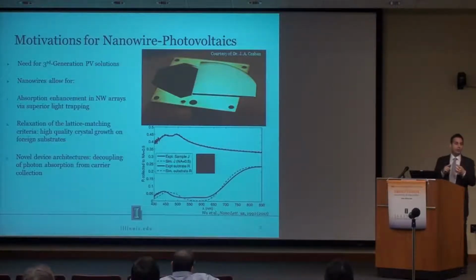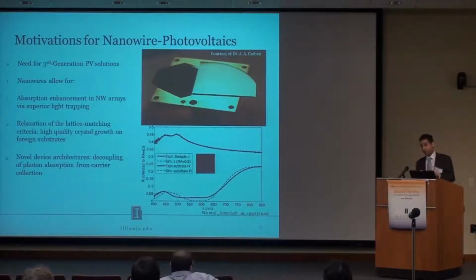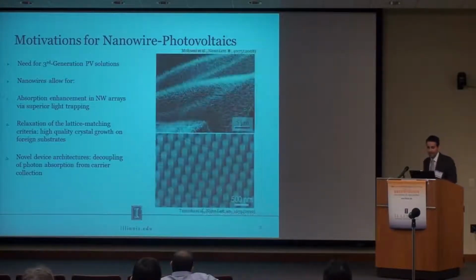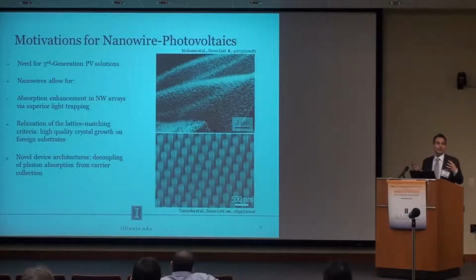First of all, the nanowires allow for multiple scattering interactions. And they also act as a graded refractive index medium, allowing for ease of coupling between air and the substrate itself, both of which allow for superior light trapping beyond the level of what can be achieved even with the best multi-layer anti-reflective coatings. Second of all, nanowires allow us to relax the lattice matching criteria for heteroepitaxy.